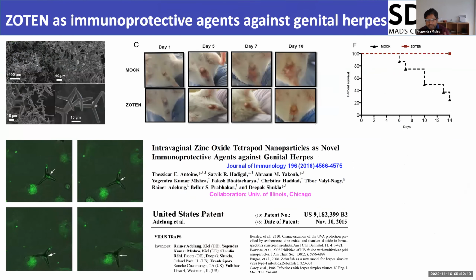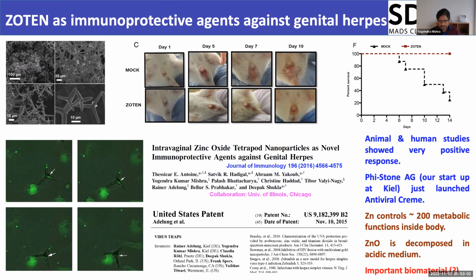To make the story short, we infected mice with genital herpes, and then we treated them with zinc oxide tetrapods, and we could see that the mice treated with tetrapods survived much longer. You see images here: this is the genital herpes virus, this is a WBC, and this is the tetrapod showing the viral binding. Basically it gives three functions. First, it binds the viruses. Second, it triggers a cell signal to the WBC to go and catch the virus. And third, a certain amount of zinc is released, which promotes cell growth, so wound healing is much faster. So this led to a US patent.